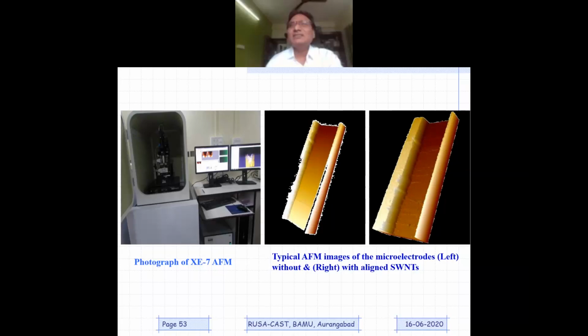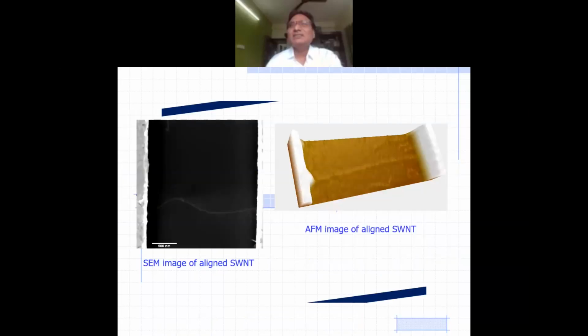However, conducting polymers also have some issues that we need to take care of. Some of the issues are low electrochemical activity and hysteresis. Obviously, we need to address those issues if we really want to use conducting polymers. And if you want to use a conducting polymer as a coating layer, we need to understand whether there would be some sort of interaction between the CNT and the conducting polymer. Through literature, we came to know that we can have a wonderful intimate contact between CNTs, SWNTs, and conducting polymer through pi stacking.